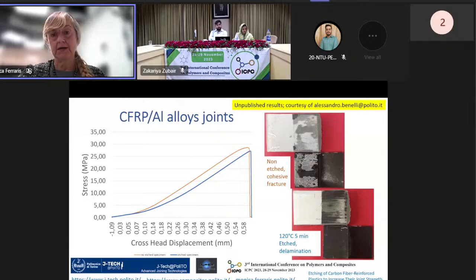So you can see there the non-etched and etched behavior. Again, these are new composite and new joints we are working on. The non-etched show a cohesive failure with no delamination. The etched one shows the etching was really effective, too much, because on the aluminum side you have part of the composite. So we are again in a situation where the etching needs to be optimized.